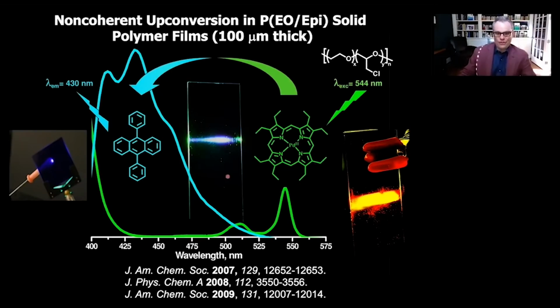So this is a really bad polymer. But this is an epichlorohydrin ethylene oxide copolymer. Terrible material to work with, but we managed to get upconverted fluorescence in thin films of this material. And then we started to play with different donor acceptor mixtures. So this is now with a phthalocyanine upconverting the rubrene.